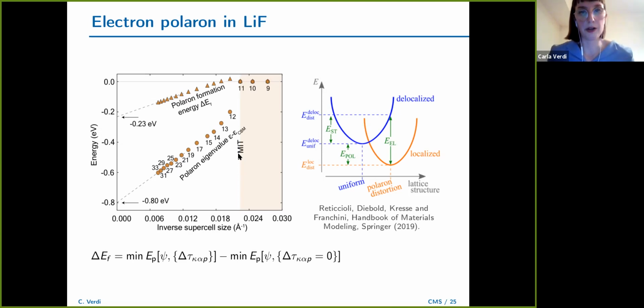What we want to say here is that if you imagine to have more than one added electron, so if you have a large enough density of added electrons, then these will not localize, but they will form delocalized states due to the interaction between each other. So this is why when you have a smaller supercell, you don't have self-localization. But in the dilute limit, you do, and this is the energetics.